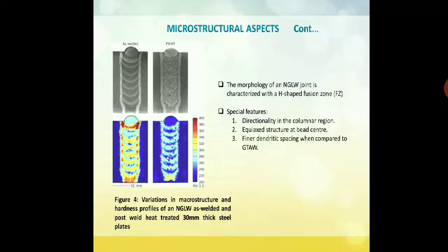They also found that the degree of the hardness was highest in the capping pass, which you can see in the figure, and that hardness is again decreasing after post-weld heat treatment. You can observe an uneven hardness in the weld joints, right? Another study reported that there is a presence of cellular grain morphology which resulted in this uneven hardness distribution.